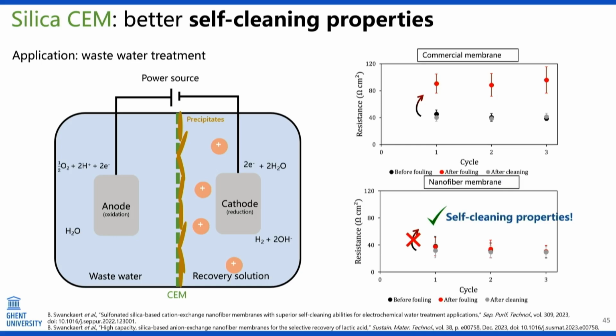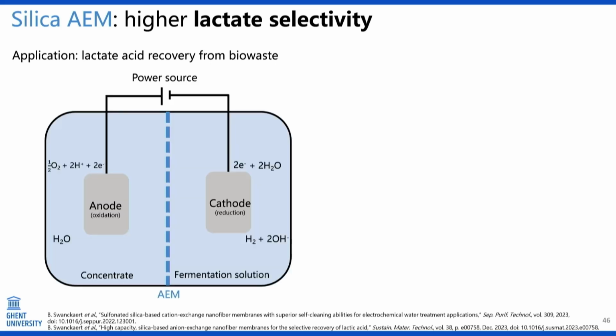Now, we showed that by using the nanofibrous membrane, just because of the nanofibrous structure, they have a self-cleaning ability. You don't need to stop the process. They foul much less, and even when they foul, if you just switch off the power source, it cleans itself, and you don't have to remove the membrane, and you can start up the process again. So that was a big advantage for these applications. Also, another thing which we want for ion exchange membranes is selectivity.